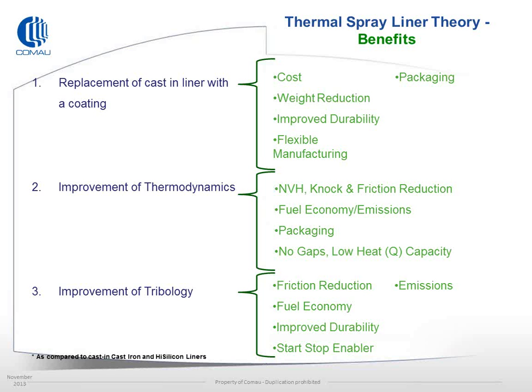Going into item 2, is the improvement of thermodynamics. We have NVH and knock, friction reduction, able to tighten up piston clearances, reduce knock potential from hot spots due to cast iron liner, which is usually caused by variation in the position of the casting. Because of the improvement in thermodynamics, there are significant improvements in fuel economy and emissions. Packaging, of course, but the biggest benefit is there's no gaps between the coating and the block surface. This is intrinsic to the process, as well as the only way, if we have a gap, we don't have adhesion of the coating.